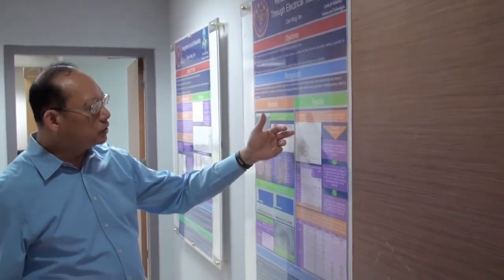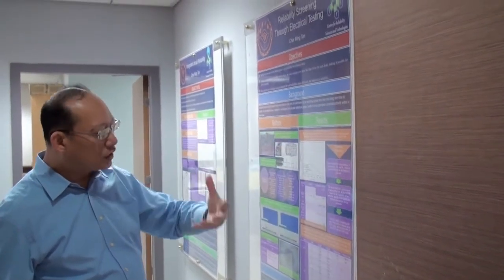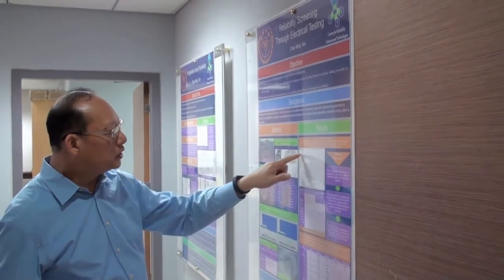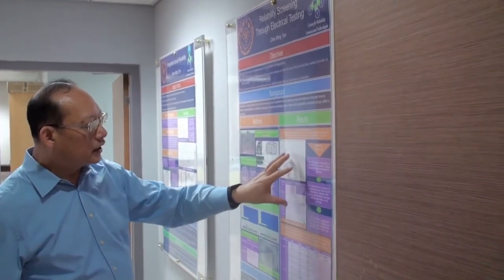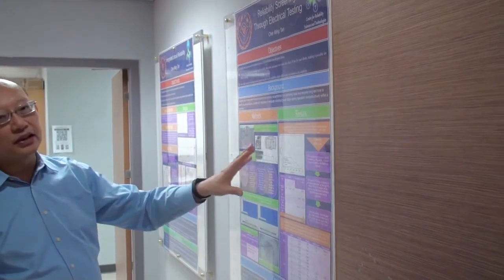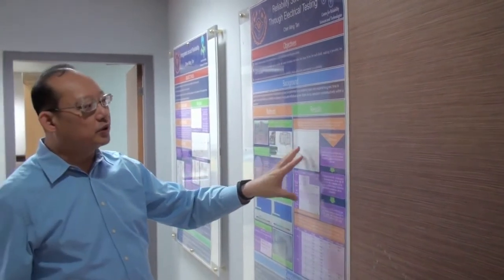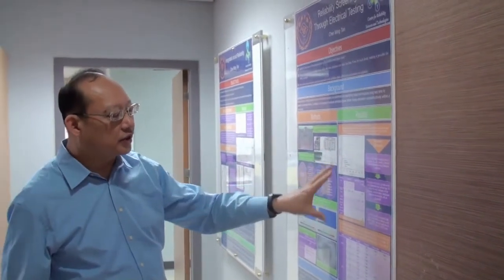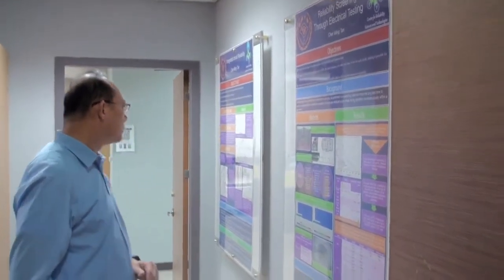But after the screening, we are able to get a good device where the reliability only decreased slightly. And the screening can be done in the order of 1 or 2 milliseconds. That tremendously helped them to screen and to ensure that the customer is receiving the good part.